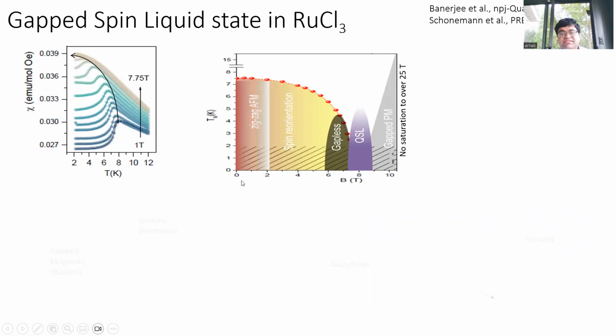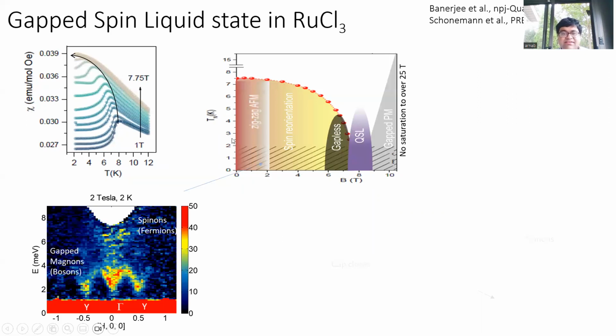What we got is that at low fields, you have a zigzag antiferromagnetic order, which goes into some kind of spin reoriented phase at roughly 4 Tesla. Then at 6 Tesla, it seems that you have a gapless phase, and then it goes to a quantum spin liquid phase.